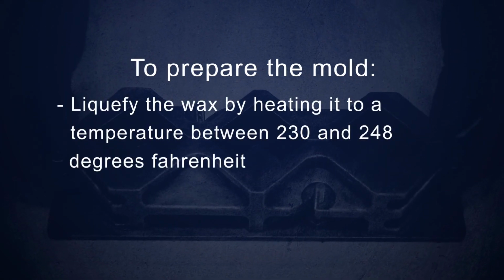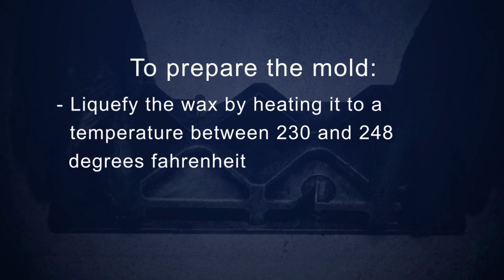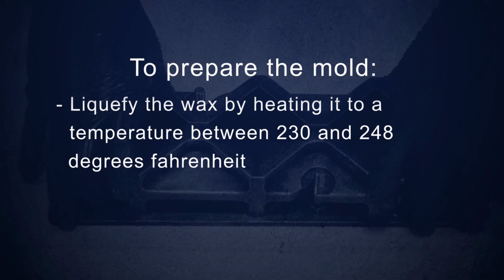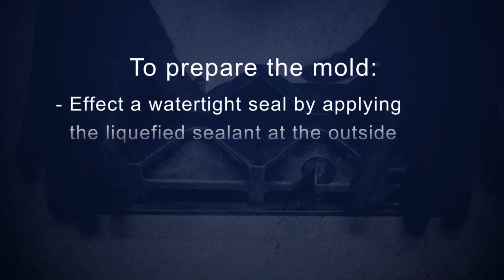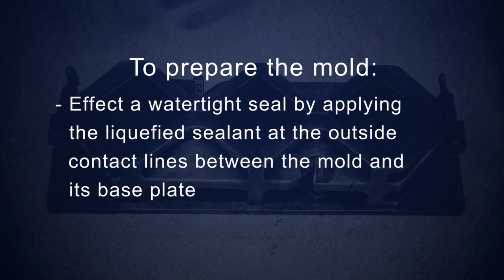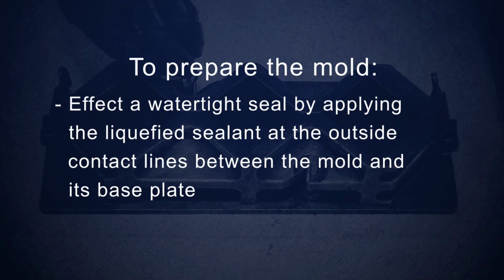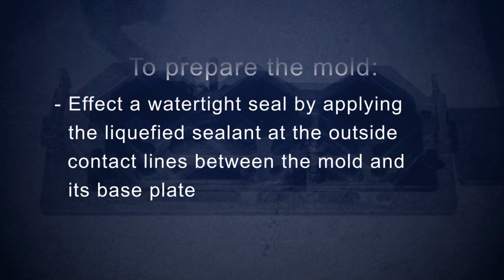Liquefy the wax by heating it to a temperature between 230 and 248 degrees Fahrenheit. Effect a watertight seal by applying the liquefied sealant at the outside contact lines between the mold and its base plate.